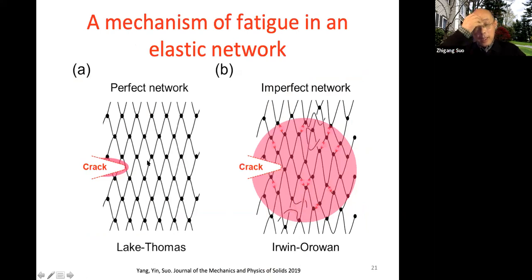Here's the mumble. A new hypothesis, why nearly perfect elastic materials can still suffer fatigue. So if you have a crack in a really perfect network, meaning each chain is identical, then you have a strain concentration, right? When the crack comes along, you break this, break this, break this. All these other things will not break. So you should not have fatigue. Either the chain breaks or you don't break. There's no fatigue. Cycles make no difference.